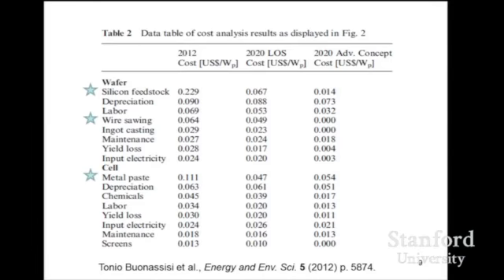If you read into this paper, you see all the costs, and some of them are going to be really hard to cut, but some of them look very promising. And so the silicon itself is very expensive. And if you can saw thinner, you can do a lot better. But if you can radically change the game there and go from 150 microns all the way down to 10, this is where you can go from about 23 cents per watt on silicon down to a penny and a half. And then, of course, if you don't do wire sawing, then you can cut that to zero.